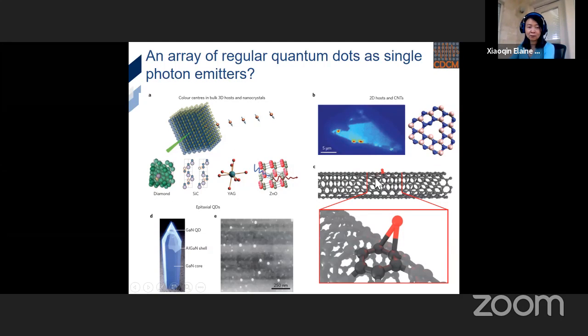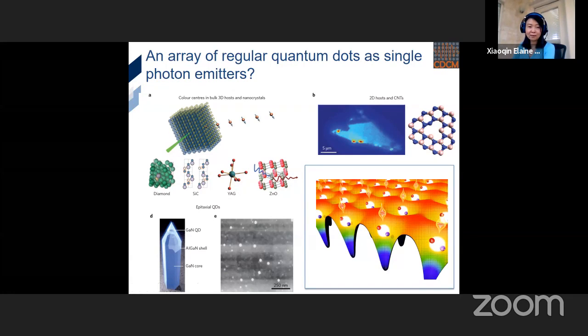But all of these single photon emitters suffer from the downside that the locations are not defined, and there are size and shape fluctuations. If we can learn how to make this Moiré cell really well, then we would provide an entirely different material platform for an array of quantum emitters. So that's one direction, and we know the energy trap is very deep. In some other material, you can have 400 meV of energy trap for the Moiré cell too.